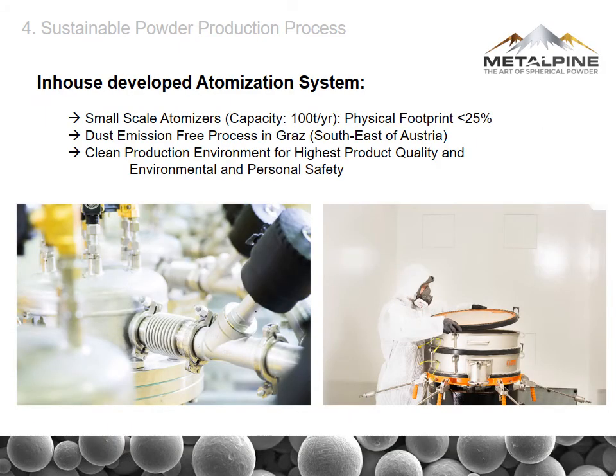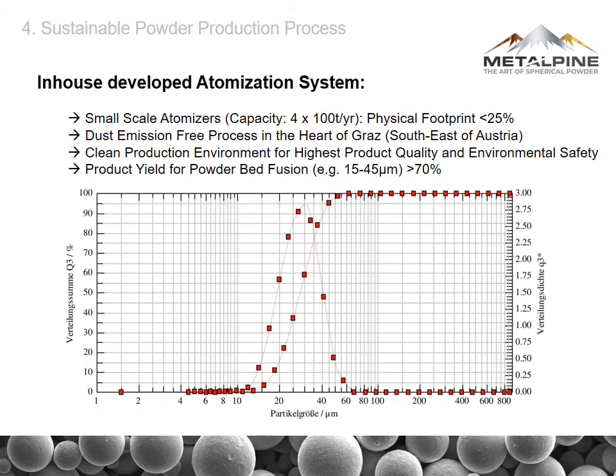Our in-house developed atomization system has got a really small physical footprint of less than 25% of that of standard atomization plants. Nevertheless, we have got a capacity of 100 tons a year for any of our atomizers. We have got a dust emission-free process in Graz. We have got a clean production environment for highest product quality and, of course, environmental and personal safety. We have got a really high product yield for powder bed fusion, for example, more than 70% for copper or nickel-based alloys or stainless steels in the range of 15 to 45 microns.